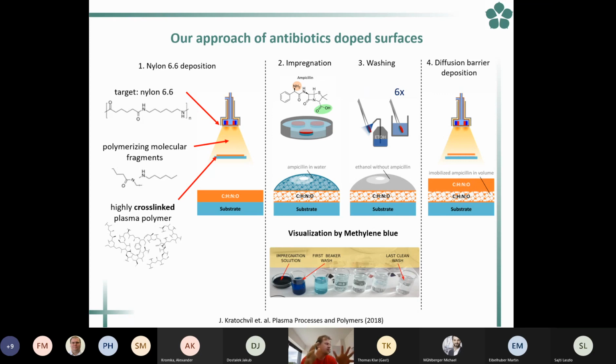chain. And these fragments are after that cross-linked in the plasma volume or on the surface, and then we are able to prepare the polymer which is cross-linked, where this coefficient we are able to tune by the parameters in the plasma. And further on, this structure we used to impregnate by the antibiotics. For example, in our case, it was the ampicillin.